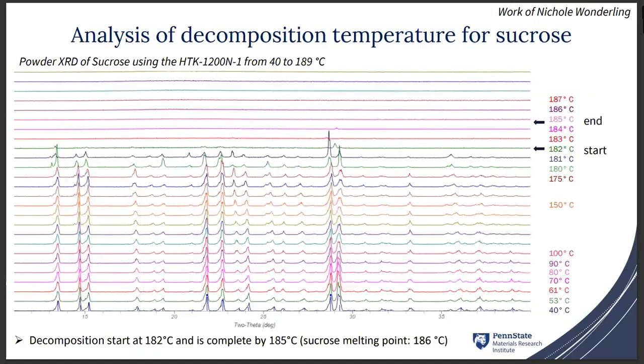Then if we look at the analysis of the decomposition temperature of sucrose over the range of temperature, we can see a start of disappearance of the diffraction pattern at 182 degrees Celsius and complete disappearance at 185 degrees centigrade, which is in good agreement with a melting point in the literature of 186.